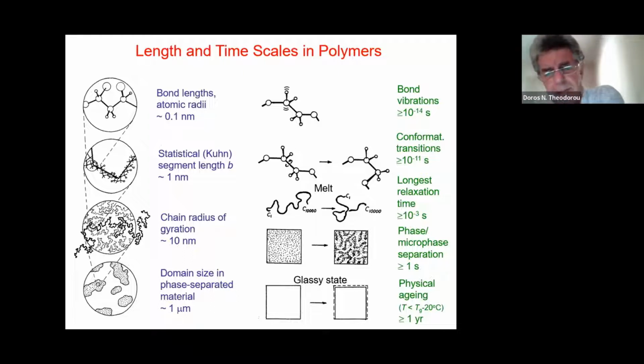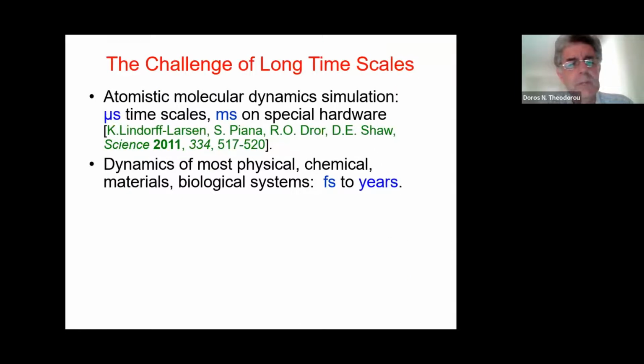If we have phase and microphase separation phenomena, these may have characteristic times of seconds. And if we go to the configurationally arrested glassy state, where the system is not in equilibrium, it is very gradually trying to reach equilibrium, the processes of physical aging 20 degrees below Tg can have times on the order of years or longer. So from bond vibrations to physical aging in the glass, we have 21 orders of magnitude on the time scale. And clearly, all this cannot be addressed by a single simulation approach.